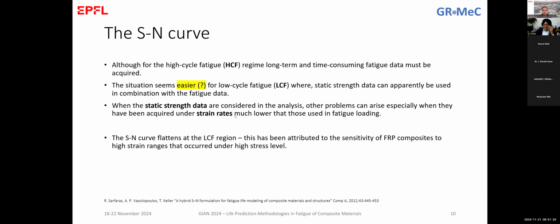So it is difficult to get data. It is difficult to get data in the high cycle fatigue because of the time that is needed there, and also because the line becomes flatter there. Sometimes we see that there is more scatter in this region, and the situation seems easier for low cycle fatigue because there you just do a test and in a couple of hours you can have your result. But there I have this question mark.